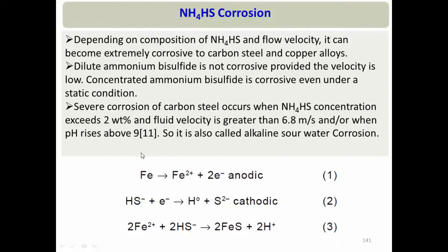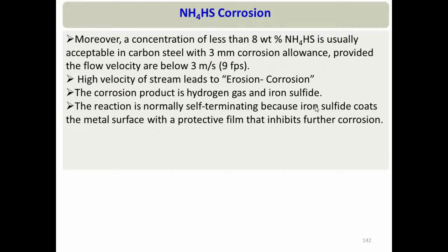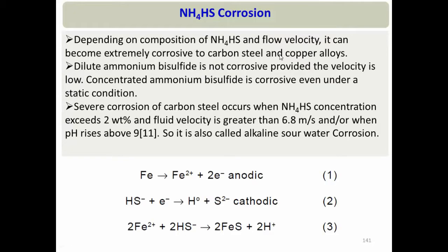If pH is very low, then this corrosion usually does not take place, because in that case the concentration of ammonium bisulfide will be much smaller. Now this is about above 2 weight percent, and we found that when concentration goes above 8 weight percent, this corrosion will take place even under static condition. Below 2 weight percent there won't be any problem. At 2 to 8 percent corrosion will take place, but it depends on the velocity of the fluid. If it is lower velocity, then there won't be any problem. But if the concentration goes above 8 percent, corrosion will take place even under static condition. So this is the key.